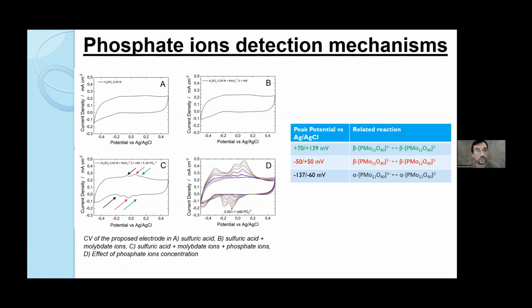By looking at the literature, we can see that these Keggin ions have two isomers, the alpha and beta isomers, that can be oxidized and reduced at different potentials that you can find in the table. Increasing the concentration of phosphate ions, as you can see, the peaks of oxidation and reduction of Keggin ions increase linearly.